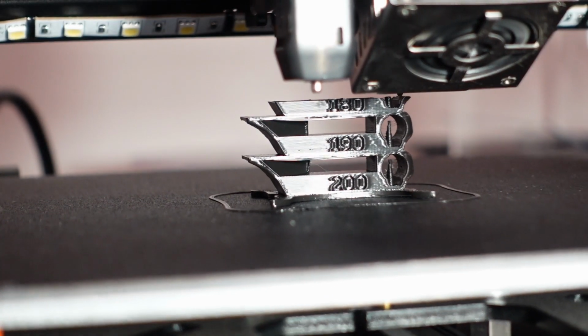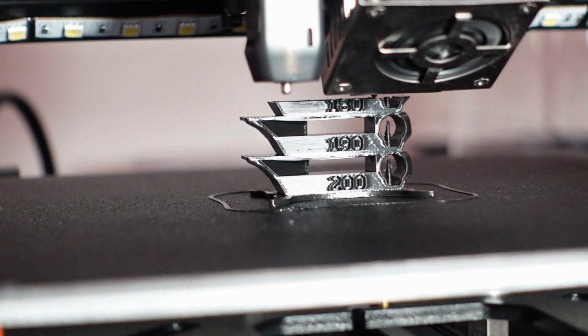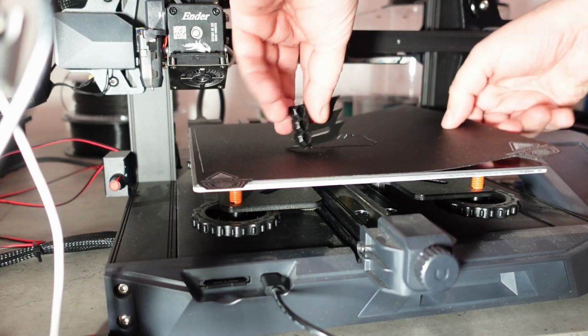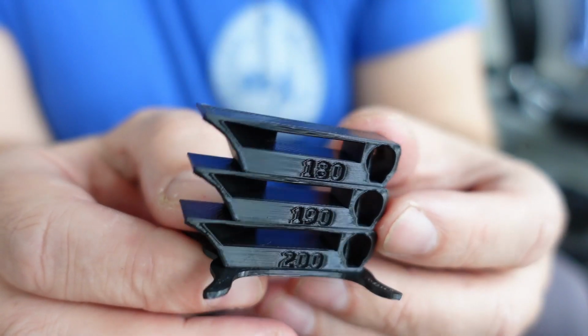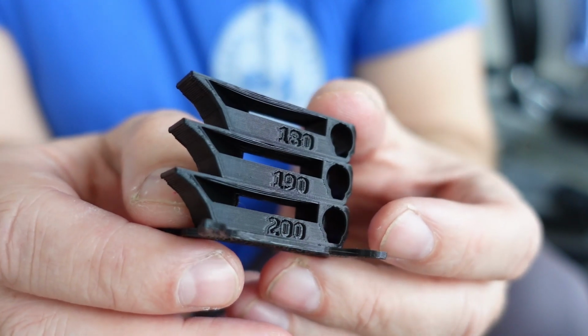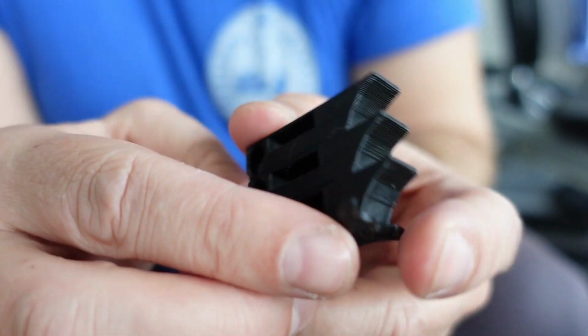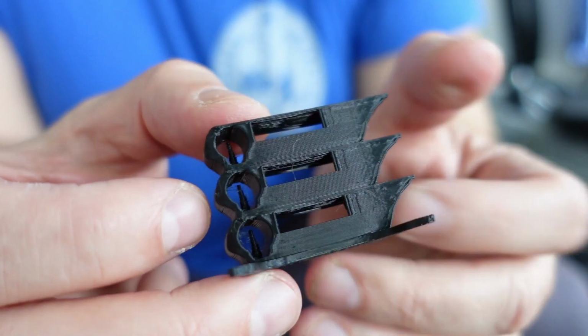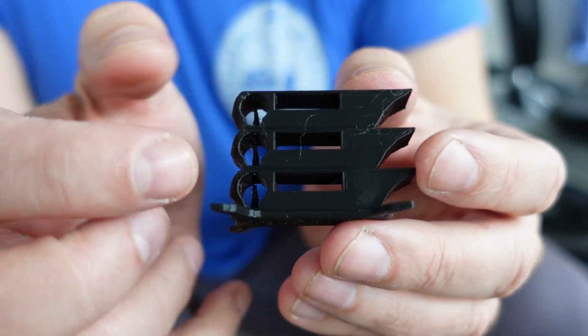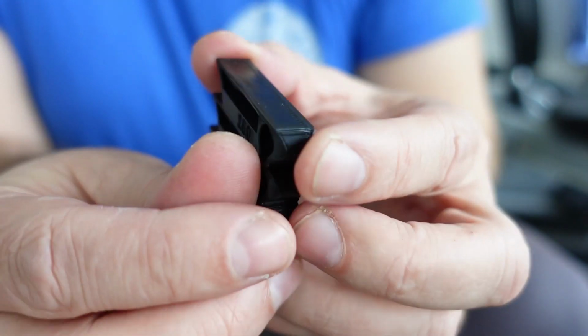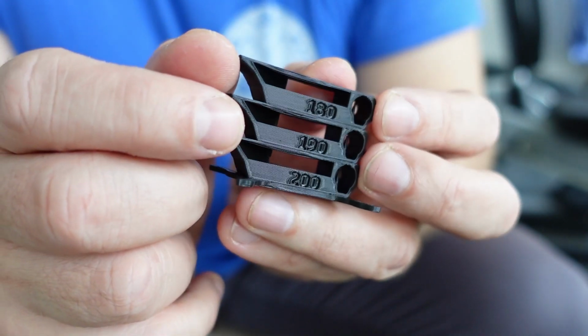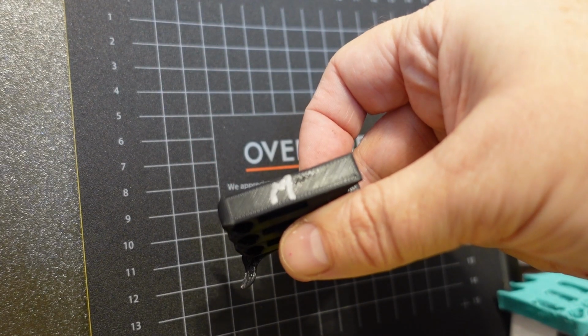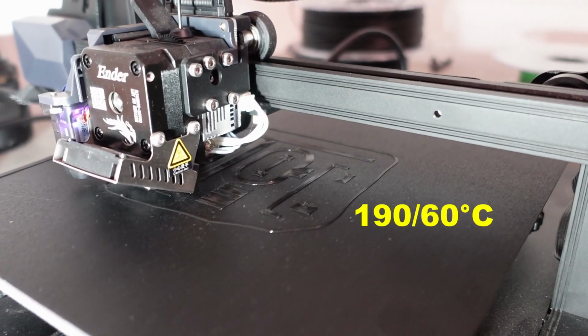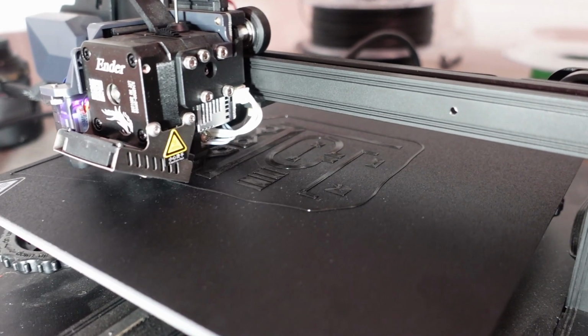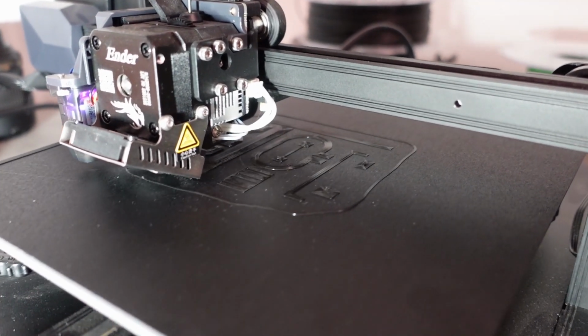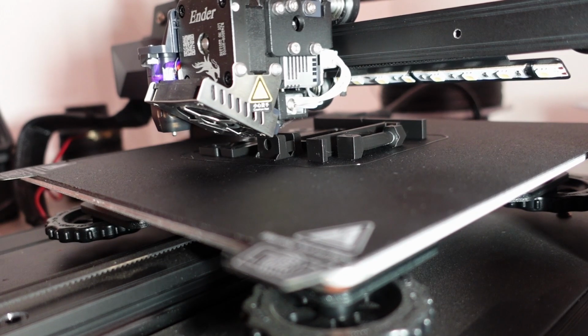I was worrying about printing on 180 degrees Celsius, but this looks okay. I cannot see any kind of error on this temperature tower. Perfect bridging, overhangs, great surfaces, absolutely no stringing on any temperature. And now I print all test objects on 190 degrees Celsius, which is in the middle of the recommended printing range. For PLA META, we use the silver marker. Again, all test objects at once on 190 degrees Celsius, and these are great first two layers. Last two elements for the layer adhesion test.